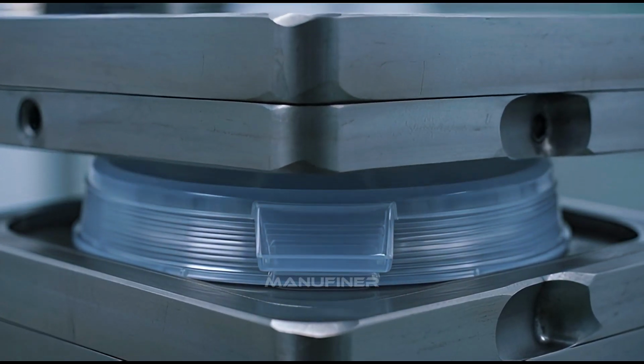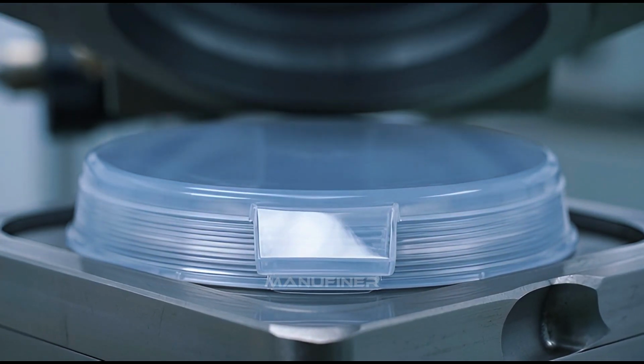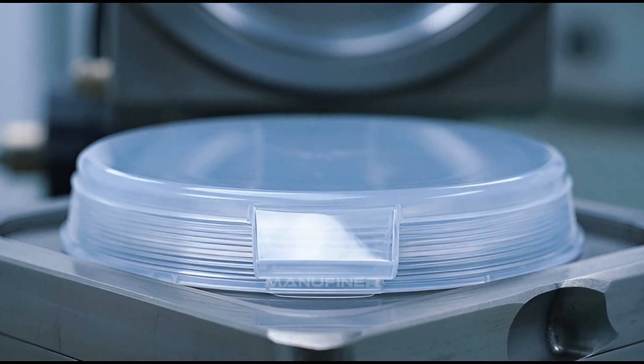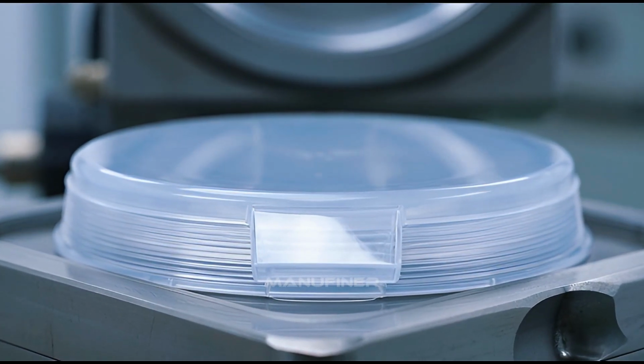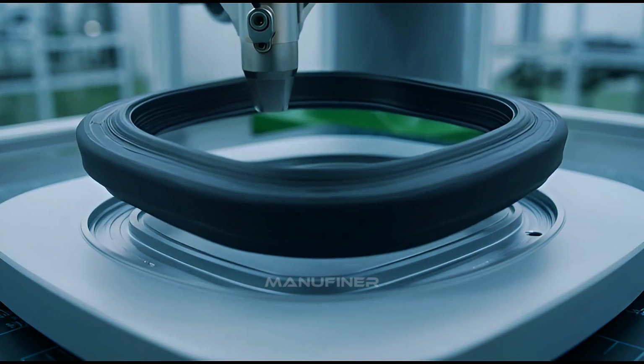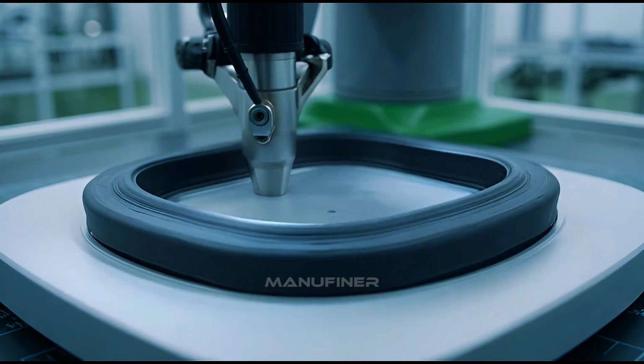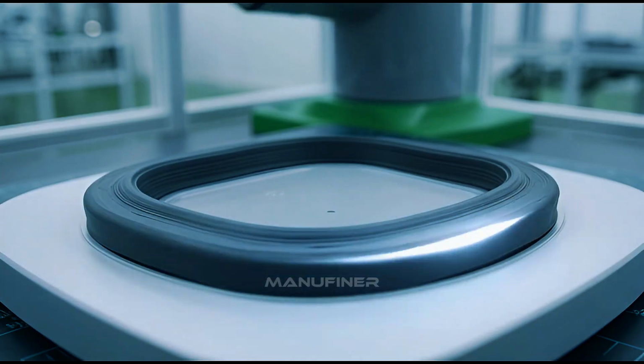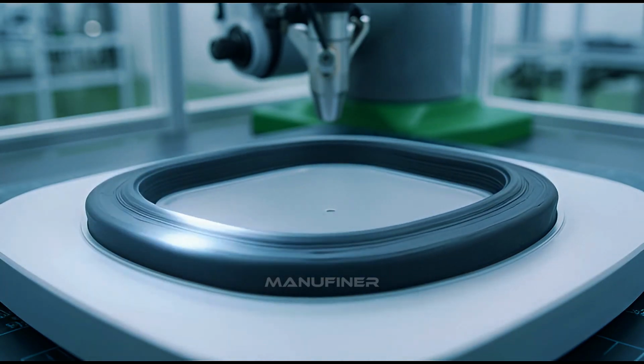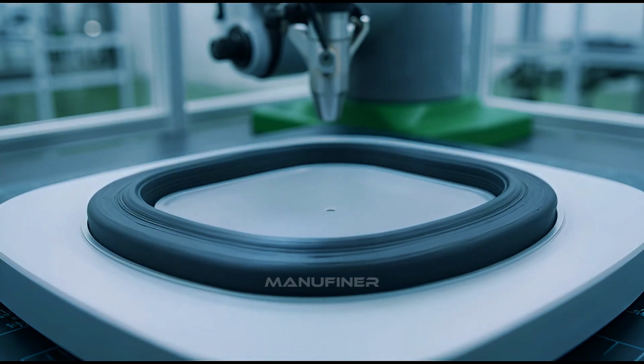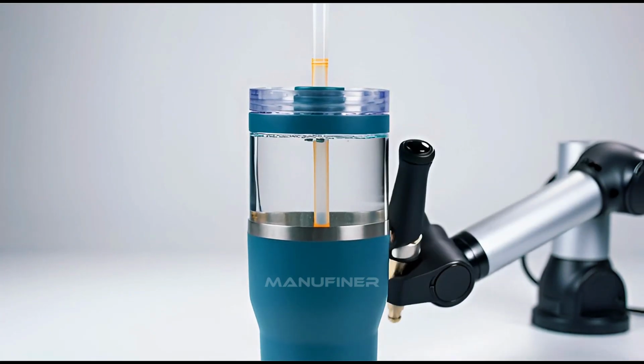Then a sample from every production batch goes through accelerated thermal performance testing, where the tumbler gets filled with ice water at a standardized temperature, and the rate of temperature rise gets measured over time and compared against the specification. This test verifies that the vacuum insulation is performing at the level Stanley specifies.